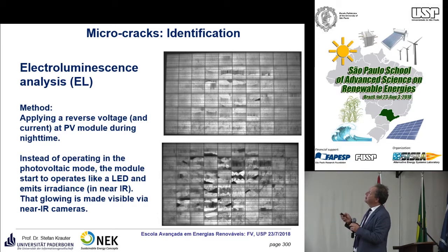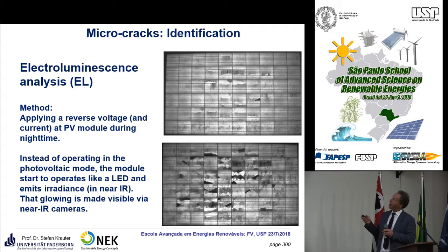Everywhere where it's light here, it's also working quite well in photovoltaic mode. So here you see there's a crack. This is isolated. So there is a crack here and a crack here, so this part of the solar cell is dead. But it's a big module, so it's not so bad. If you stand on the module, you see damages like this. Here, these areas are dead. So these are invisible cracks, very small cracks. You cannot see them visibly, but with the electroluminescence method, you can make them visible.